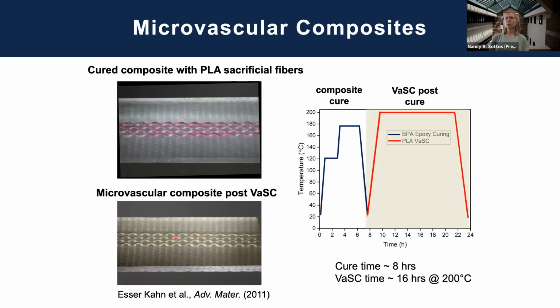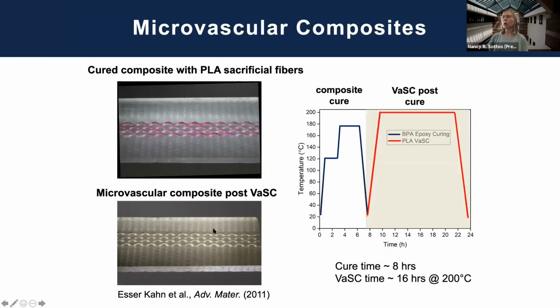And what we wind up with is this beautiful composite with vascular channels. But to make this composite on the bottom, we had to go through the conventional cure cycle. So in this case, it was an 8-hour cure cycle. And then what we called a VASC post-cure, which actually took up to 16 hours at 200 C. So while it was quite successful, we weren't worrying about the energy it took to do this.